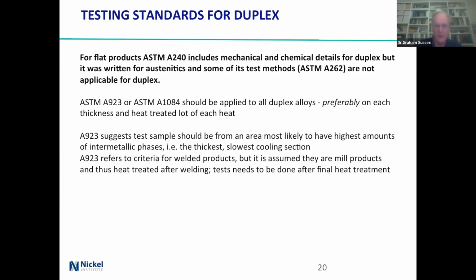923, I did say that, I hope, are likely to have the highest amount of intermetallics because they're thicker, usually, slow cooling, and so you may well get intermetallics as you're welding them. It has criteria for welded products. It has been assumed in there that they're mill products, and so they've been heat treated after welding. If you have tests done after that, well, you really should do them after final heat treatment. I've got to say that that's observed more in the not doing it than in actually complying with it, but that's the way the rules work.